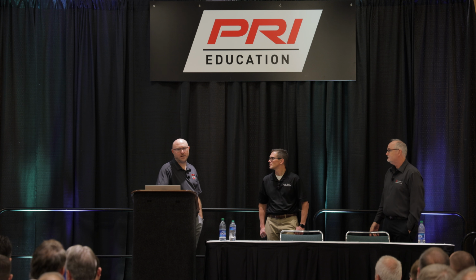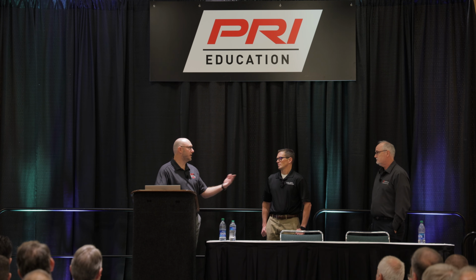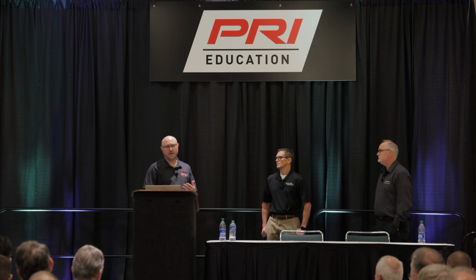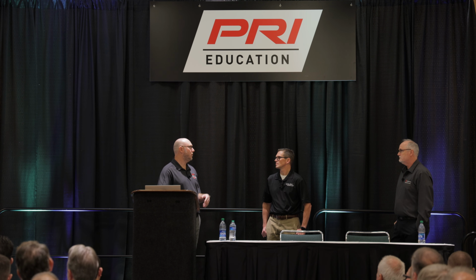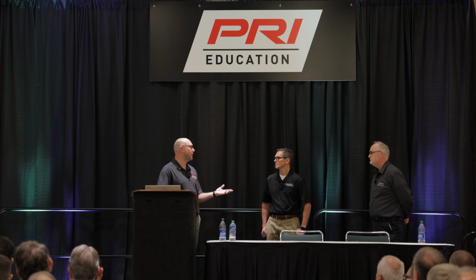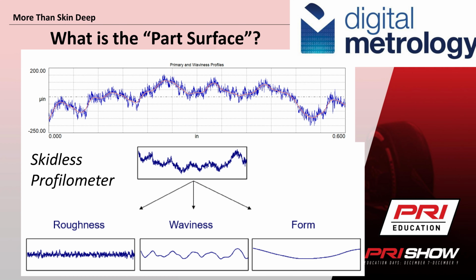Yeah. So when we talk about the surface, and we talk about grinding versus turning a piece, and we're talking about this scale of microns, we're doing that so we understand what part of it, when we talk about the surface, are we really talking about in this little tiny scale? So, what part of the surface is the surface, right? Yeah, and so you look at this, it's plus 200 microinches, minus 250 microinches. And you can see this whole trace, this is what you would get with the skidless profilometer going across, with the diamond looking at the whole surface. You can see we have contour here, we have roughness, we have waviness. And so you break it up and we can look at what's the roughness, what's the waviness, and what's the form.